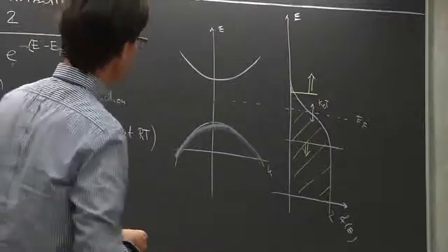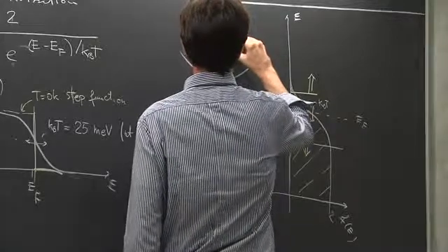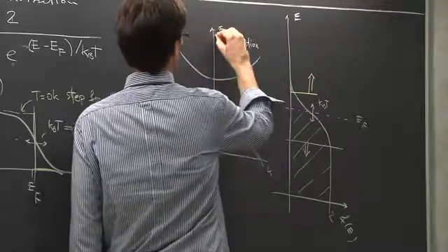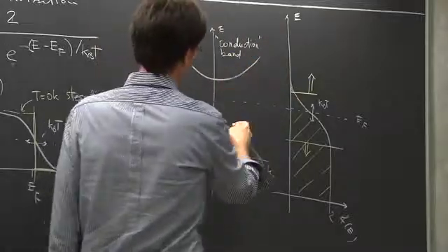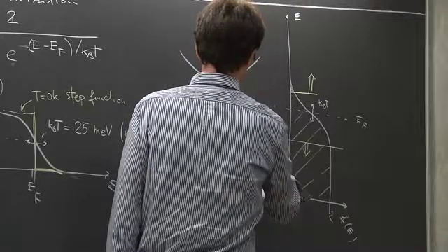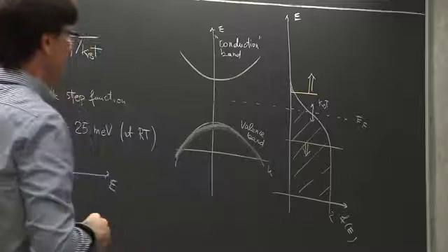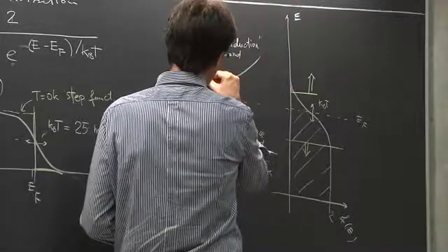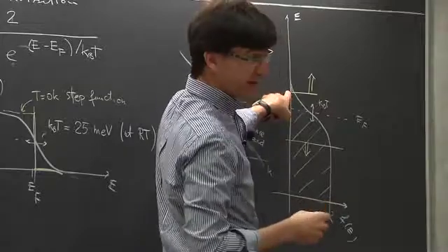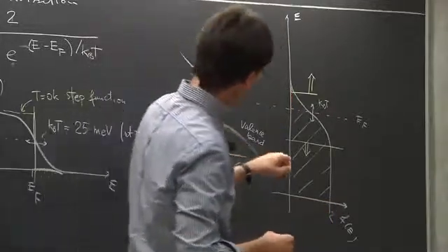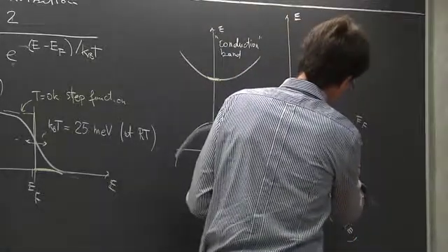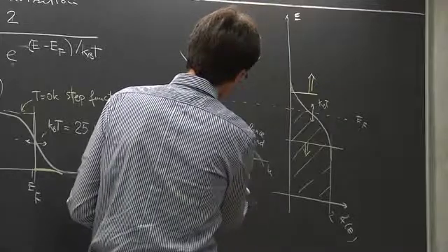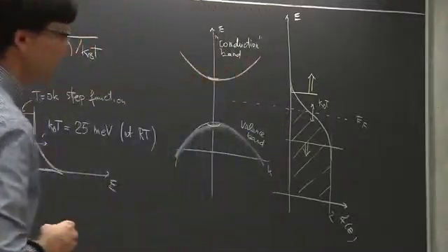Actually, let me give it a name. In the language of semiconductors, this band here goes under the name of conduction band, for reasons that will be clear in a minute. So this is the so-called conduction band, the one right above the Fermi level, and this one is called the valence band, the one right below the Fermi level. So we obtain an occupation number which is small but finite in the conduction band. Similarly, there will be an exponentially small departure from the value of 2 here. So there will be a small depletion of electrons close to the top of the valence band.